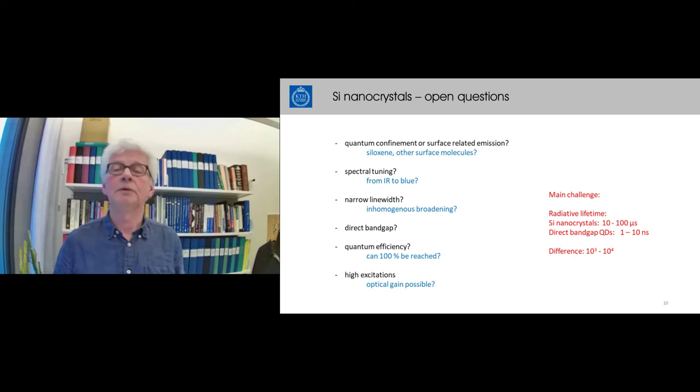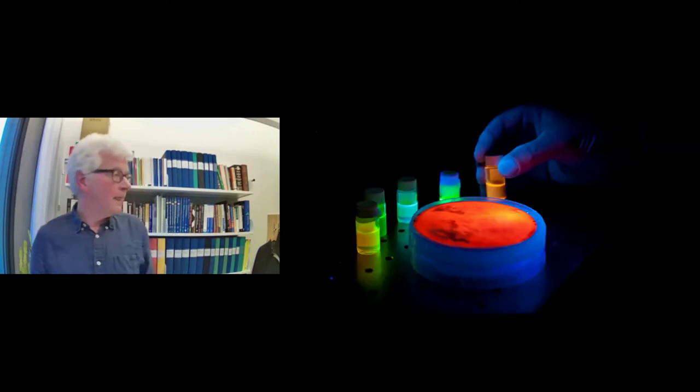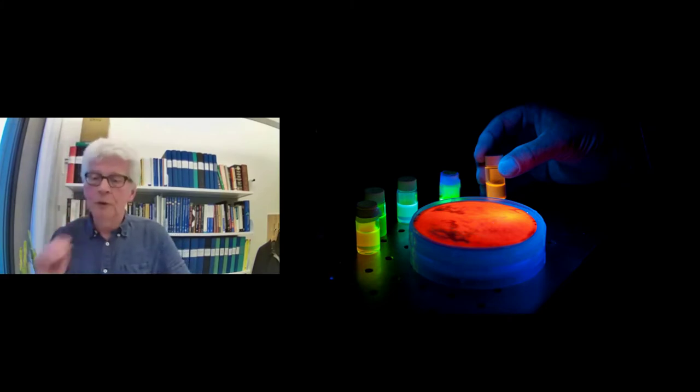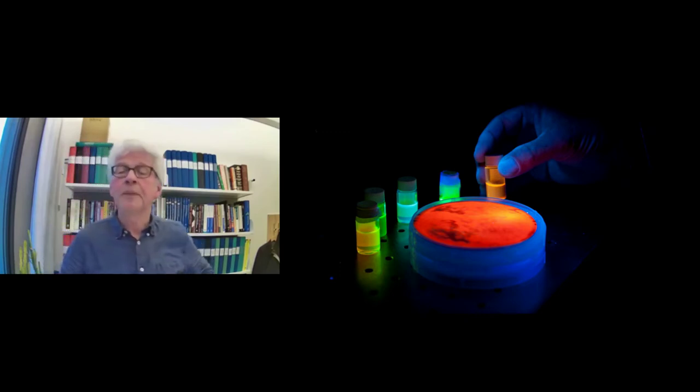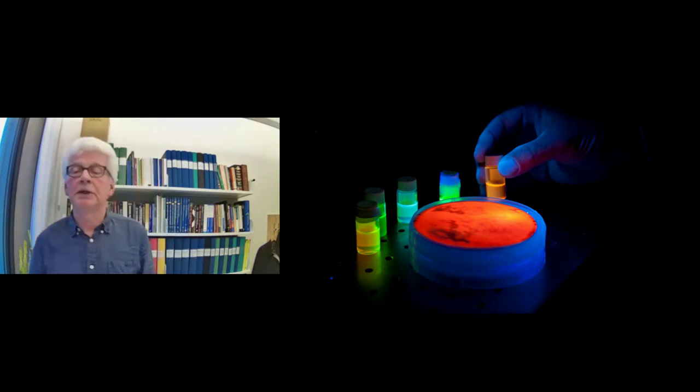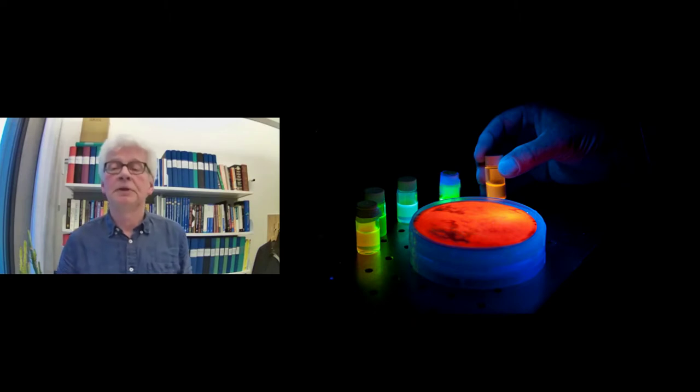Our main challenge here is that the radiative lifetime of silicon nanocrystals has been found to be 10 to 100 microseconds while that of direct band gap quantum dots is only some nanoseconds. The difference is huge. And experimentally that means that your experiment will be much longer if you want to probe a single quantum dot and detect the same amount of photons. If you do one day of experiments on the direct band gap quantum dot, if you do that on our silicon quantum dots, it would take maybe 10 years to probe the same, to get the same number of photons. This is a photo that we took when I started this with a master student in 1994. This is the wafer of porous silicon, it's a four inch wafer. It's compared here to cadmium selenide nanocrystals which are dispersed in a toluene solution. Remarkably what you can see here, the intensity excited by UV, intensity almost the same. That's because the quantum efficiency is probably something like 10% and it's similar here.